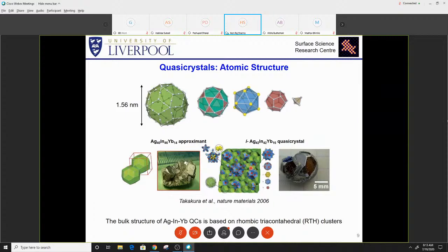Of course, in this case, you need to fill the gaps in between the clusters with atoms. But more than 90% of atoms belong to clusters, and the rest can also be predicted. Again, small changes in chemical composition, from 30 to 40, lead to a crystalline structure. So I'm trying to indicate that quasicrystals are often very complex in terms of structure and chemistry. So we like to have as simple a quasicrystal as possible.